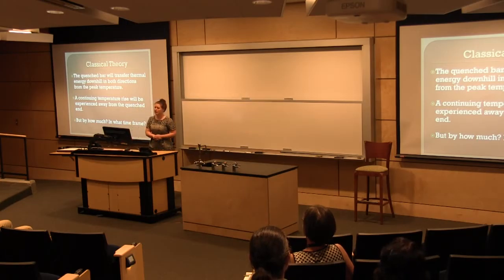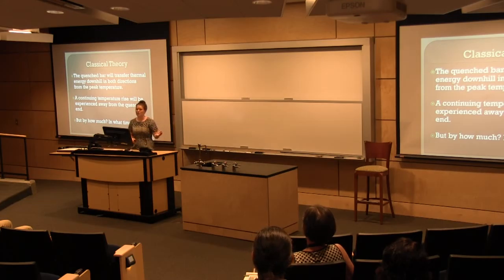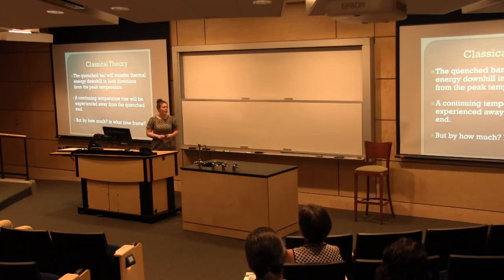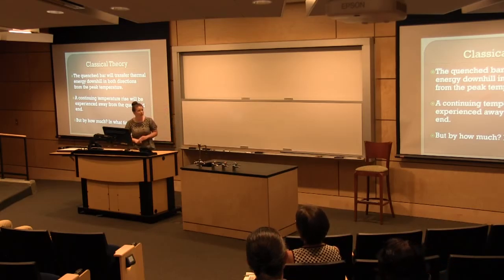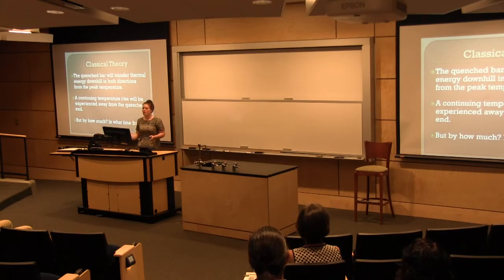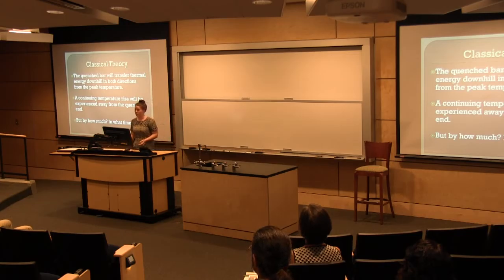In terms of classical theory, when you're quenching a bar, there's obviously going to be heat transfer into the water coming off the one end, and there's going to be heat transfer along the bar in the other end. And then the temperature will continue to rise in the rest of the bar on the other end when you are quenching in terms of classical theory. But the interesting thing for our research, at least, is this last bullet point, which is by how much and in what time frame. So we're actually aiming to say that we're seeing a greater rise in temperature than classical modeling, and we're seeing it in a faster time frame than the classical model.